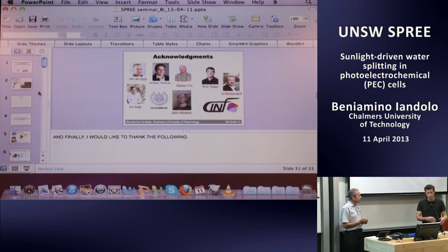Well, we did some calculations where we tried to model this adhesion layer with a combination of, say, half titanium oxide and half titanium, and also changed the relative amount of titanium and titanium oxide. The reason why we prefer titanium is that it gives us a better correlation with experiments, because when we have pure titanium oxide, the main plasmonic peak does not shift as a function of hematite thickness. So we think that this layer, at least when it is based on titanium, is not completely oxidized. I haven't shown it here, but if we use silicon oxide instead, which is more fully oxidized, we do not see the same shift experimentally in the optical extinction. Okay. I'm not quite sure what that means, but it's something we could also try experimentally, at least in principle.